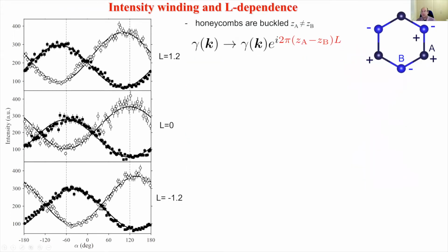fact that the honeycomb is not planar, but is actually buckled. So the A and B sublattices are not at the same height, normal to the plane, but one is below and the other one is above the plane. And if one considers then hopping of magnons between the two sublattices, then in this hopping term, there's an additional phase factor associated with the projection of the wave vector onto the Z direction.